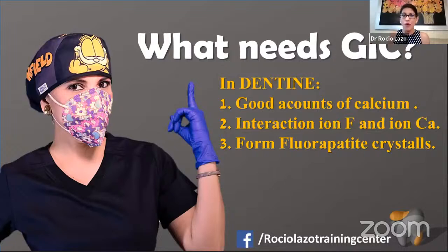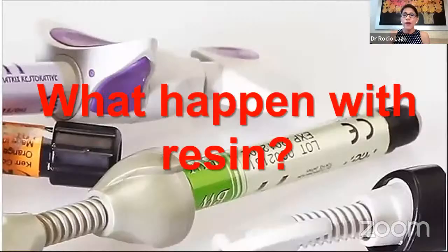The classic glass ionomers need good amounts of calcium in the affected dentin for interaction of fluoride ions with this calcium, to form fluorapatite crystals for remineralization. This is a problem with the classic glass ionomers. And what is the problem with the resins? What happens with the resin? Why are the resins not a good option for affected dentin?